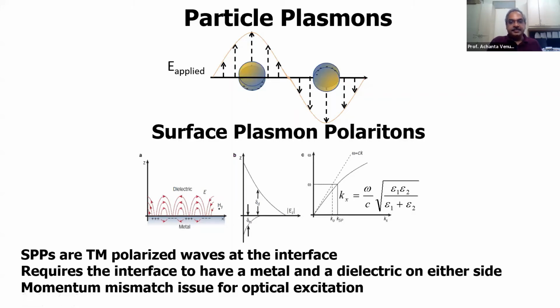If you look at it from the basic physics point of view, when we do the Snell's law derivation starting from Maxwell's equations, we look at solutions for the reflected and the transmitted components. But with the same set of equations and the boundary conditions applied, if we look for the conditions under which we have a propagating wave along the interface direction, then we do get solutions. For that, you have a dispersion relation like this for this propagating mode, which is a curve given by this solid line. And more importantly, epsilon 1 and epsilon 2 should be opposite in sign. If epsilon 1 is positive, epsilon 2 should be negative, and vice versa. Epsilon 1 positive means it's a dielectric, and epsilon 2 negative means it's a metal. So a metal and a dielectric are needed to have this charge density wave, and the dispersion is known.